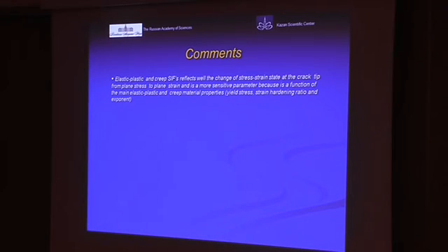And finally, some comments about my presentation. The elastic plastic and creep stress intensity factor reflects well the changes of stress-strain state at the crack tip from plane stress to plane strain, and is the most sensitive parameter because it is a function of elastic and plastic material properties.